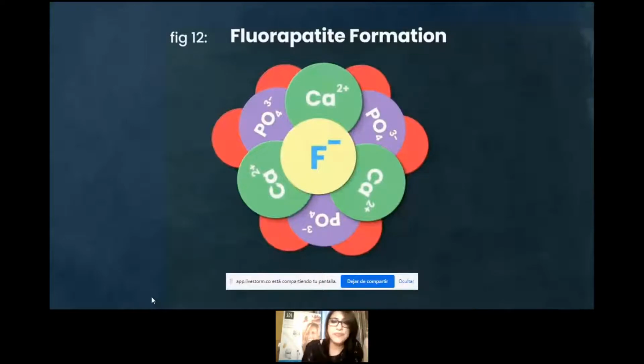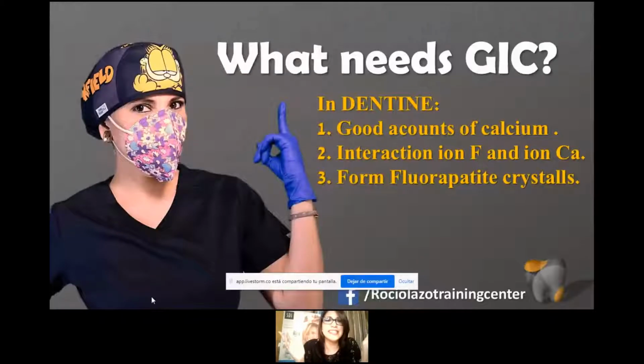This is remineralization. And what do glass ionomers need in dentin to have 100% success in our treatment? First thing, we need to have good amounts of calcium. But remember, affected dentin has more organic matrix than inorganic matrix, okay? So the amounts of calcium are not going to be so high. The second thing, glass ionomers need interaction of fluoride ion and calcium ion for remineralization, and of course, to form fluorapatite crystals. Not all the time you will have good amounts of calcium and this good interaction of ions, fluoride and calcium.